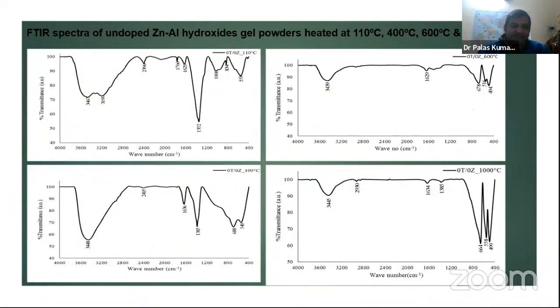So now this is the FTIR study, the Fourier transform infrared spectra. This is recorded for undoped, 0T and 0Z batches and for the heat treated versions at 400 degrees centigrade, 600 degrees centigrade, and 1000 degrees centigrade. Our main objective is to see at what temperature which kind of bond formation occurs.